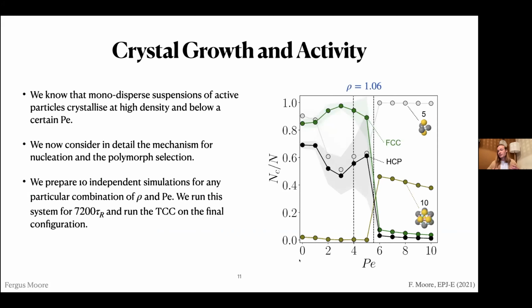So without self-propulsion, without activity, Peclet 0, you see that the difference between the two crystal polytypes is very little, with a slight preference to FCC, as has been reported before. But as you add activity, you see that the population of FCC increases to the detriment of HCP, up to an interesting point here where the gap then reduces again, and beyond which the activity is too high to nucleate crystals and you get a liquid, which is when you see the prominence of these fluid structures 5 and 10.